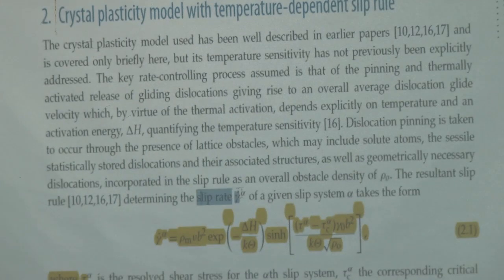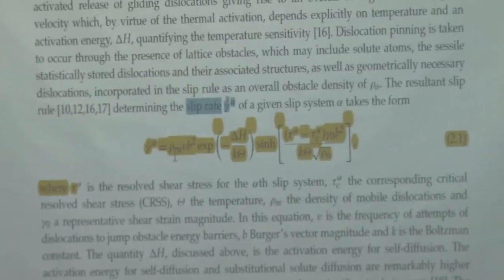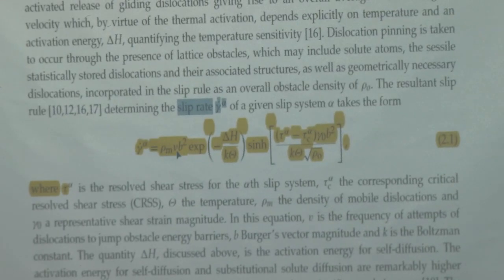I wanted to show you this equation here. You remember we were talking about the strain rate sensitivity parameter? So here is gamma dot alpha, which gives you the slip rate essentially. This is your mobile dislocation density. This is the frequency at which the dislocations are trying to jump the barrier. Burger's vector, activation energy, delta H, activation energy for self-diffusion.